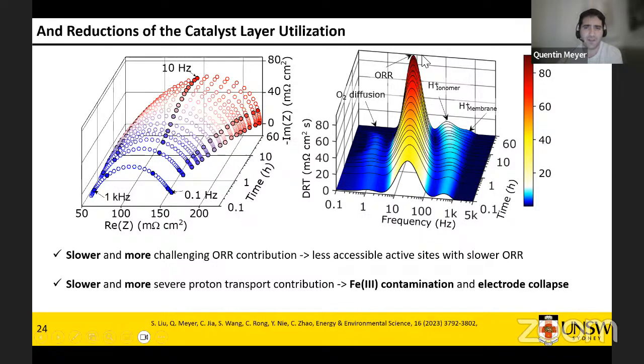And that's how you end up with some much, much slower process happening at much lower frequency and gives you high resistance. The other way to look at it, and these two could be linked, is that there are other theories that explain that you have highly active sites, but very unstable.